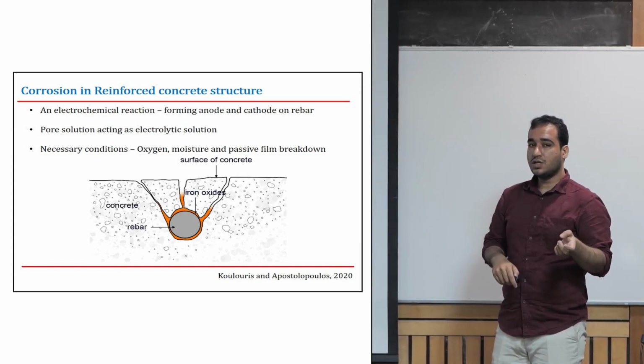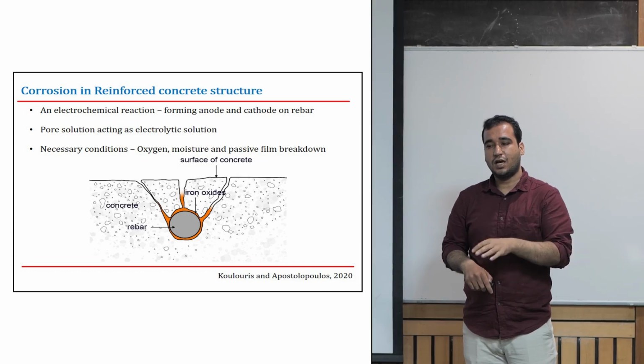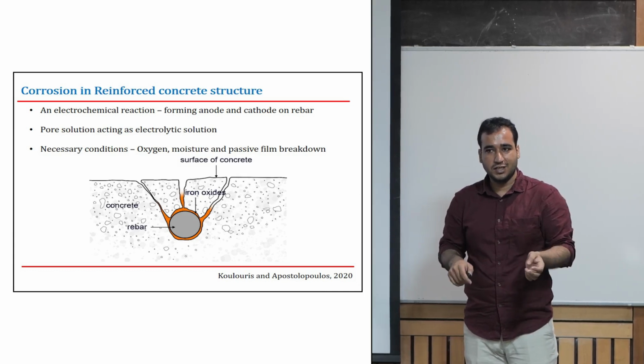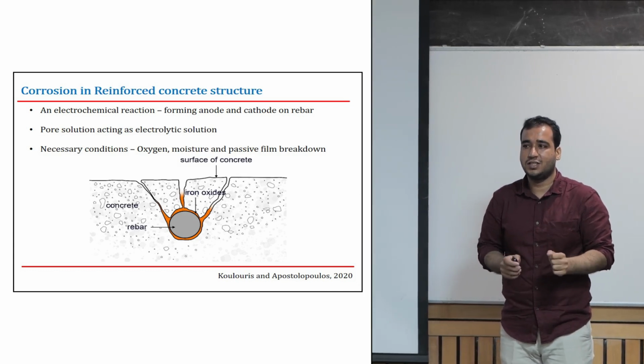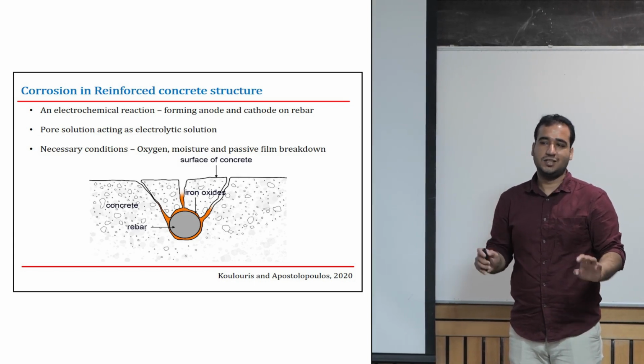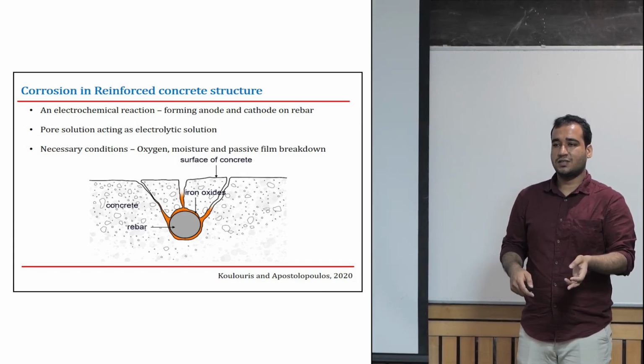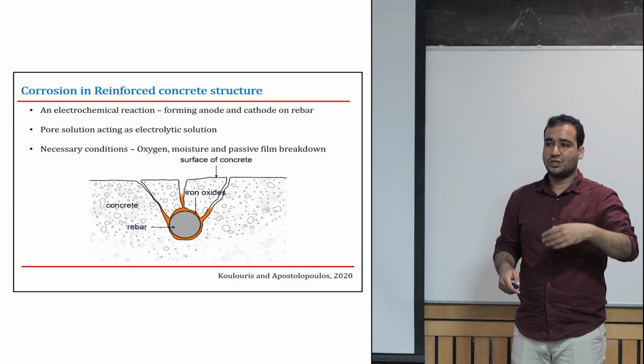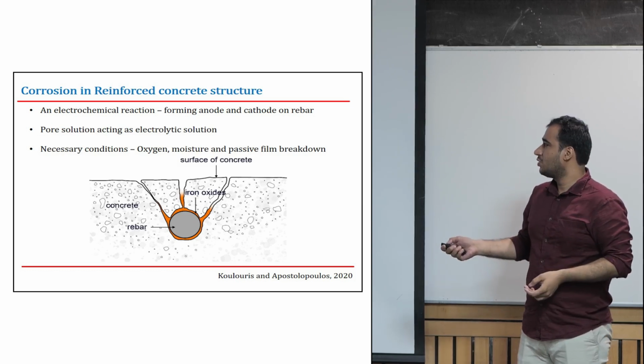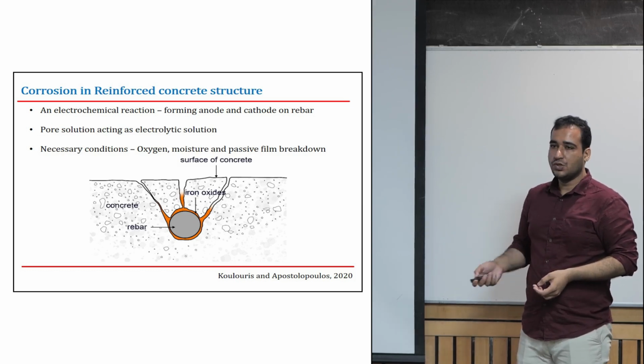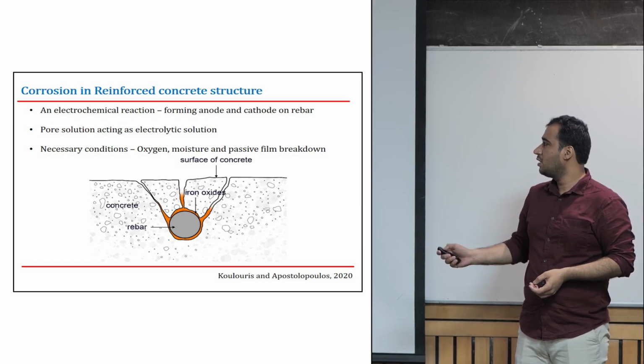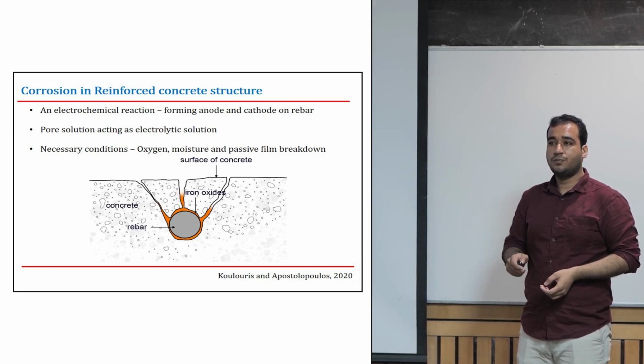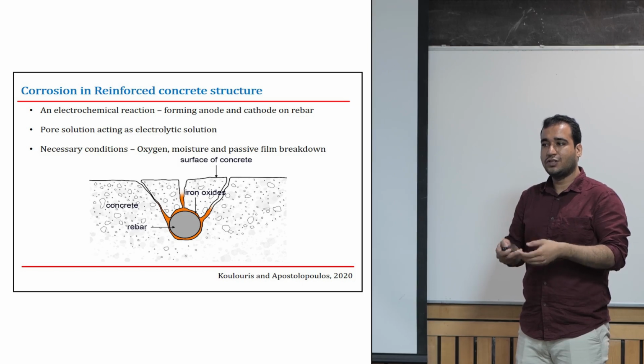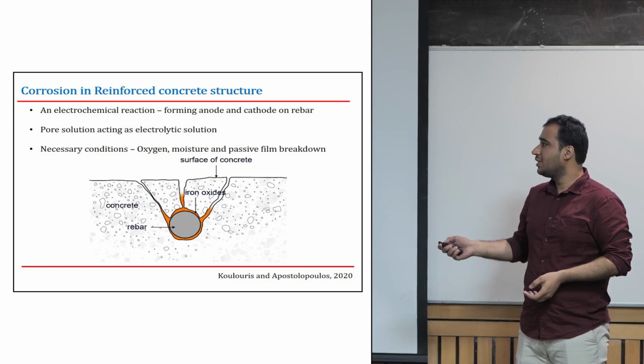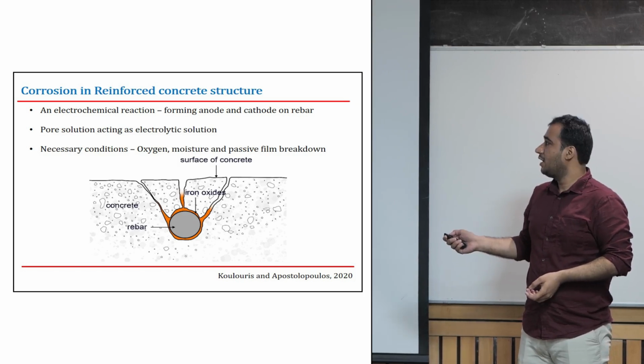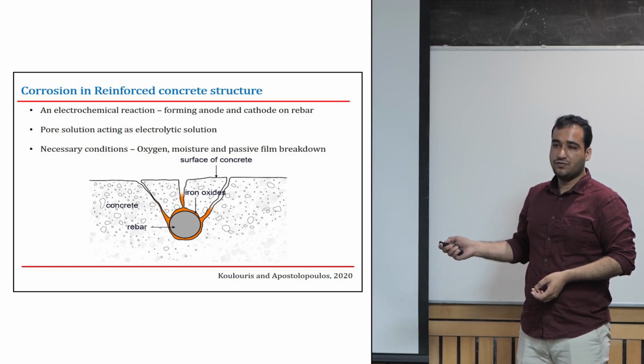Now, corrosion doesn't start with just chlorides reaching it. There are certain necessary conditions. When all of them are met, only then will the corrosion be there. Otherwise, it will just be waiting for the other condition to come. So, one is oxygen. You need oxygen at the level of the rebar. Another is moisture. You need pore solution. If you have water, only then will you have pore solution. So you need moisture at the level of the rebar, and you need a breakdown of the passive film.